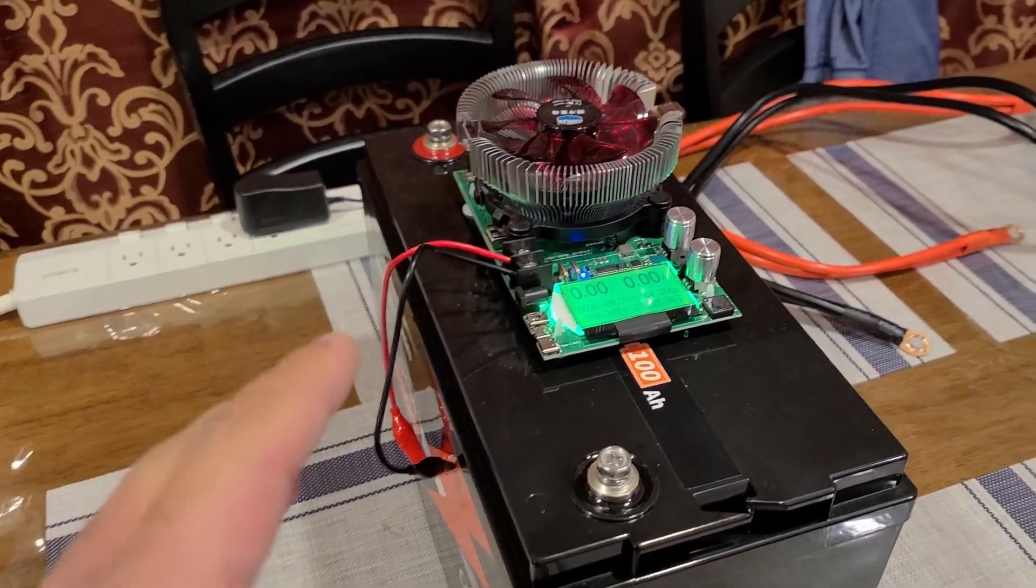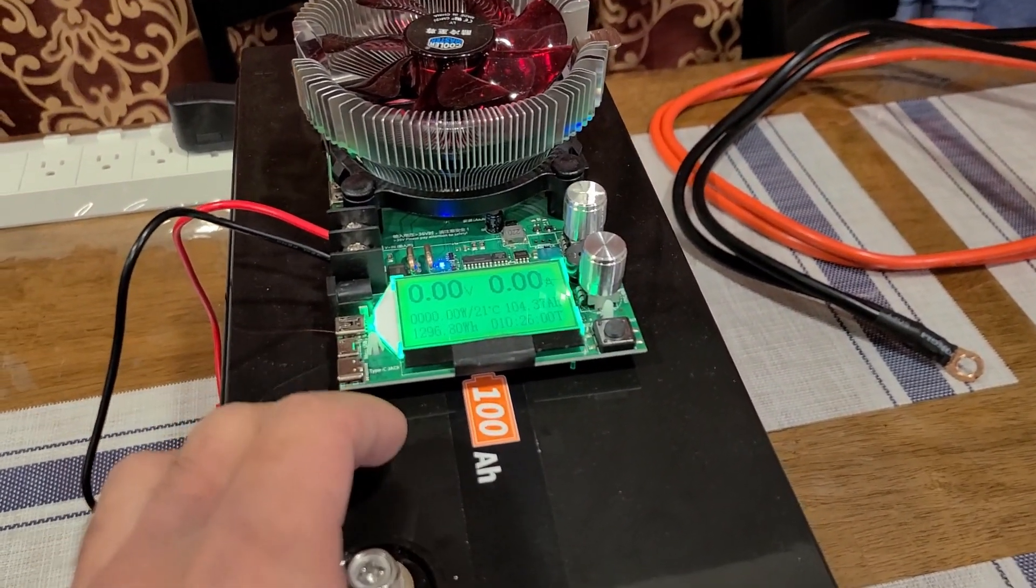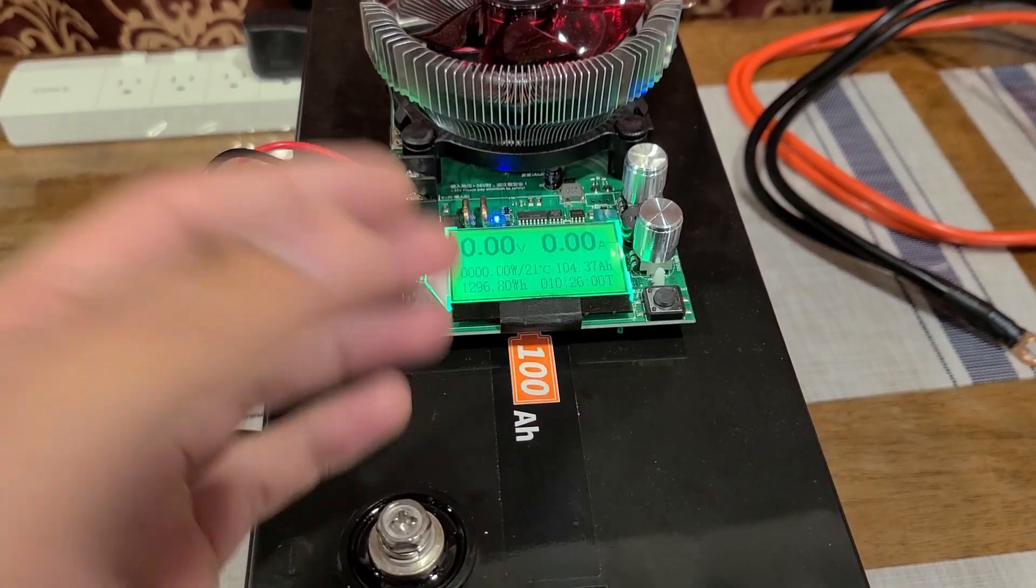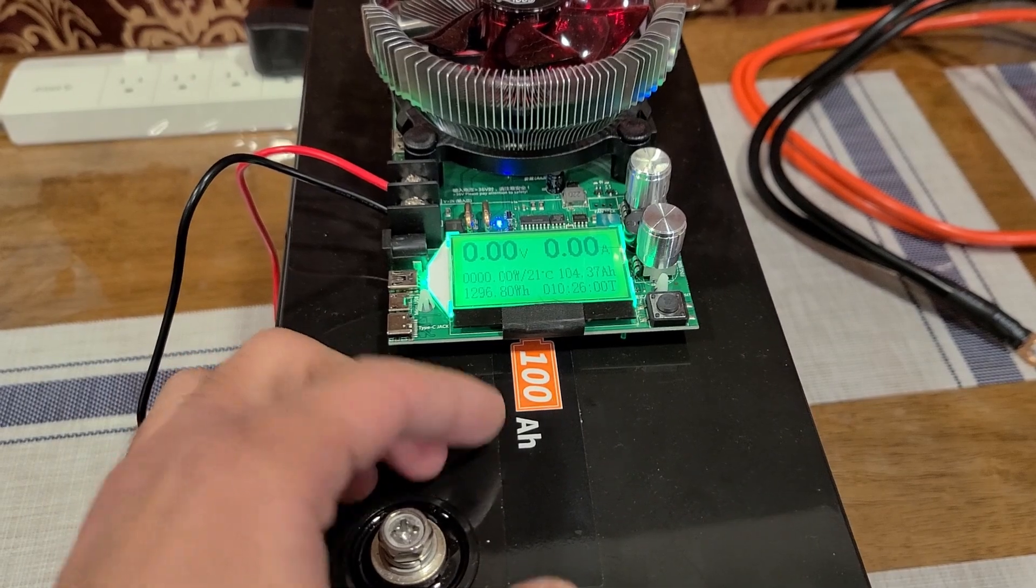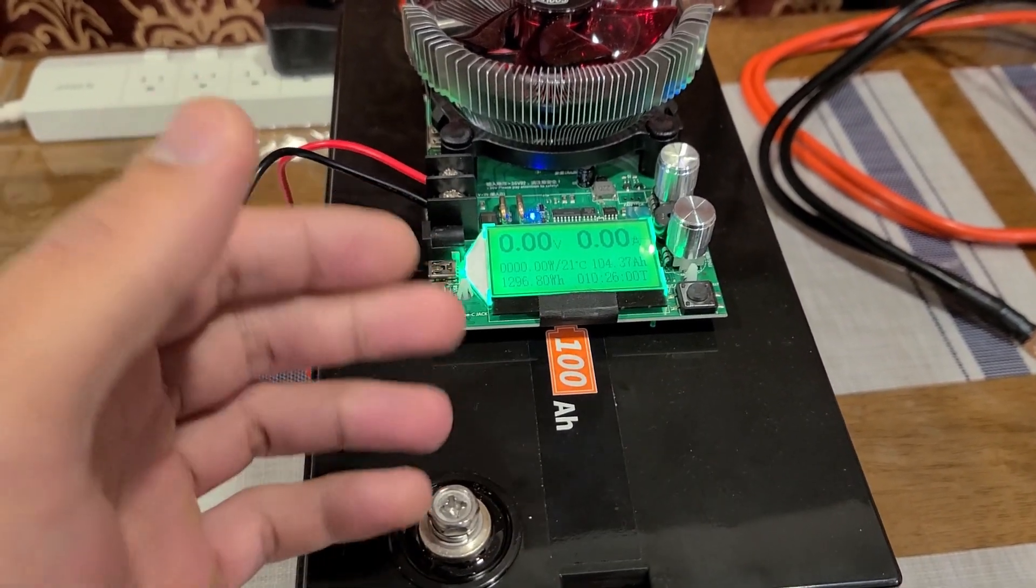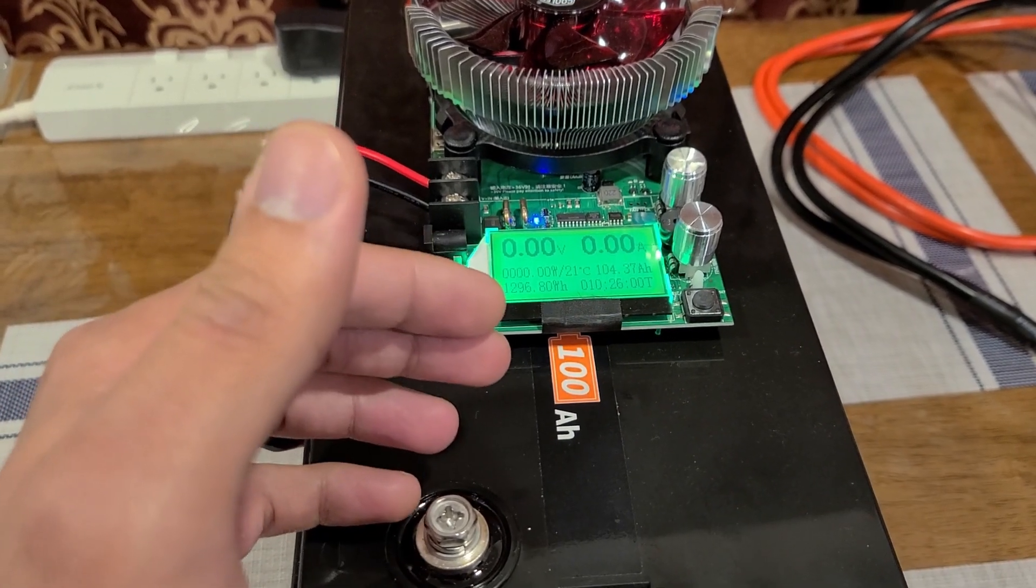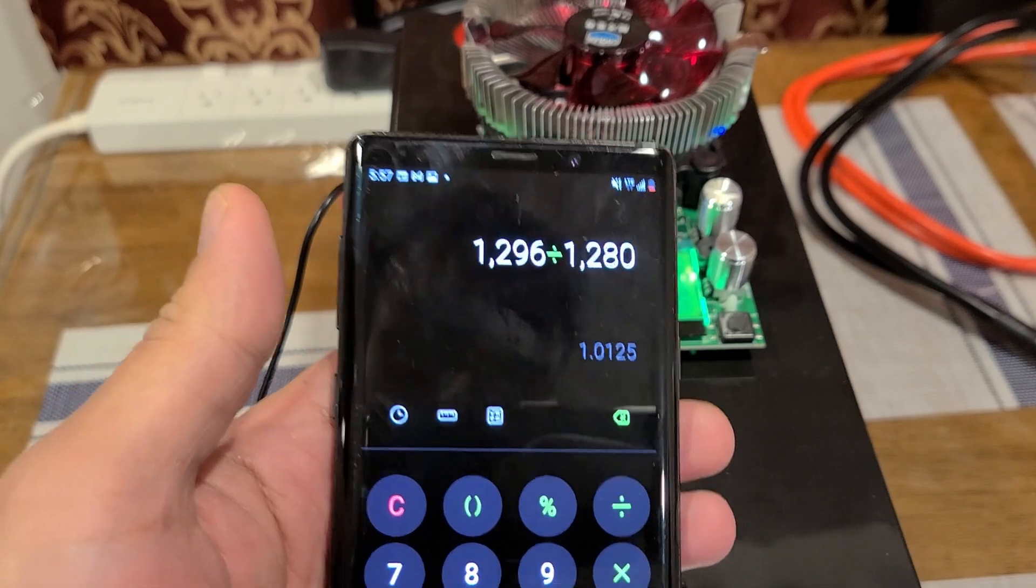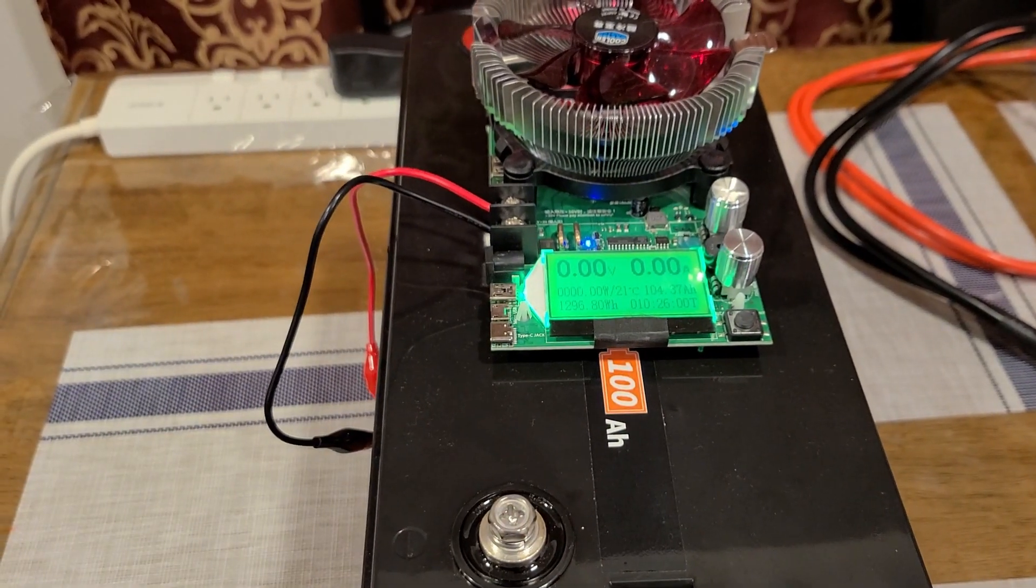All right, so after about 10 hours and 26 minutes I ended up with 104 amp hours. That's about 104 percent efficiency because this battery has a 100 amp hour capacity, so on the amp hour side it did great. Also on the watt hour side I ended up with 1296 watt hours, and doing it on a calculator that gave us a 101 percent efficiency rating on the watt hour side.